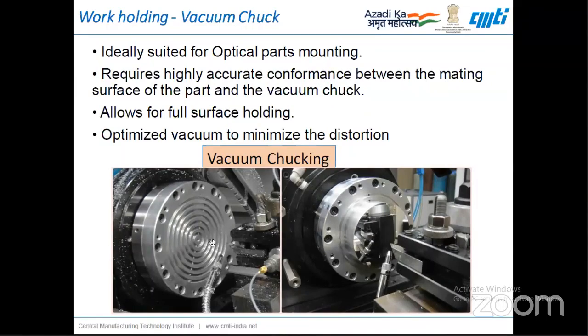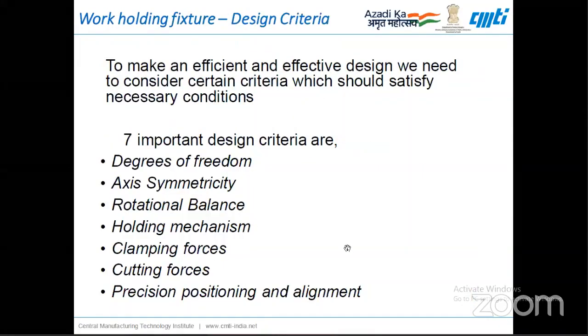If such vacuum fixturing is not available, what happens when we machine a spherical profile and then remove the component is that it gets distorted by microns, which may not matter in a normal lathe process. But in ultra precision machining, it affects the component at the micron level. So your accuracies will go poor on the component. So this chucking mechanism is very important in these machines. And basically, there are multiple design criteria if you want to design your own work holding fixtures for this diamond turning process.